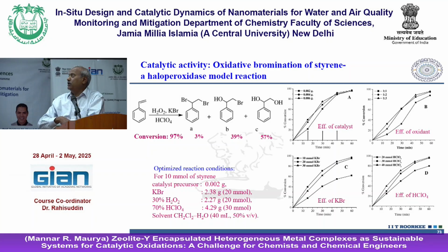So we have tried the bromination of styrene. In this case, we observed the formation of three products: one dibromo, one monobromo with a hydroxyl group, and the other a diol. And if you look at that, first the optimization, obtain the optimized reaction conditions and do the bromination. Fantastic reaction.